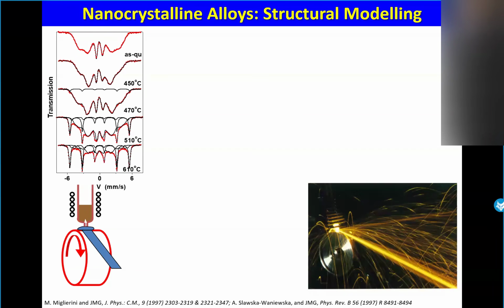So as you can see there, a series of spectra. You can see the pure sextet after heating at 450 Celsius. Without crystallization, you will see a change of the intermediate line. Why? Because you are relaxing the internal stresses. And by relaxing the internal stresses, because such systems are magnetostrictive, you will also change the orientation of the magnetic moments. So you will have a kind of rotation, either from within the plane to out of the plane or from out of the plane into the plane. It depends on the positivity or negativity of magnetostriction.